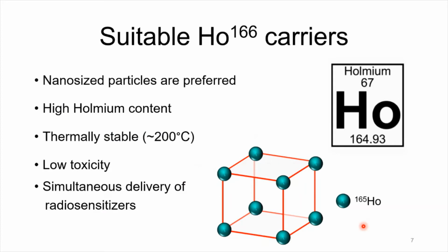Suitable Holmium-166 carriers should preferably be nano-sized and should have high Holmium content. We're talking about more than 33 weight %. They should be thermally stable. We calculate that in the neutron activation chamber, it gets to temperatures of about 200 degrees. So if your material decomposes below that, it's not good.